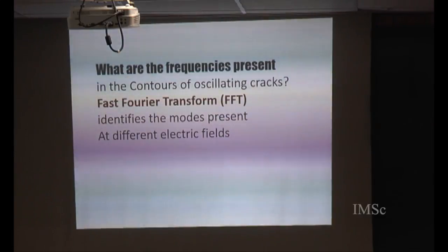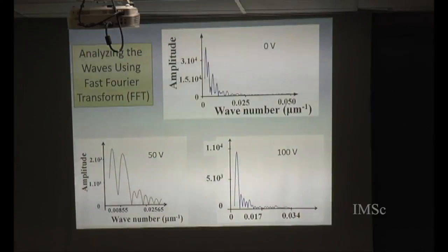Now, what we tried to do is to analyze the contours of the crack to see what the different modes present are. Because you have seen that without the field, the crack is not a purely sinusoidal mode. Though it has some regular wavy nature, it is not a single sinusoid. But for 100 volts, we got an outline which is almost a pure sinusoid. So we did a fast Fourier transform of the outline to find out what the frequencies, or rather the wavelengths, present are.